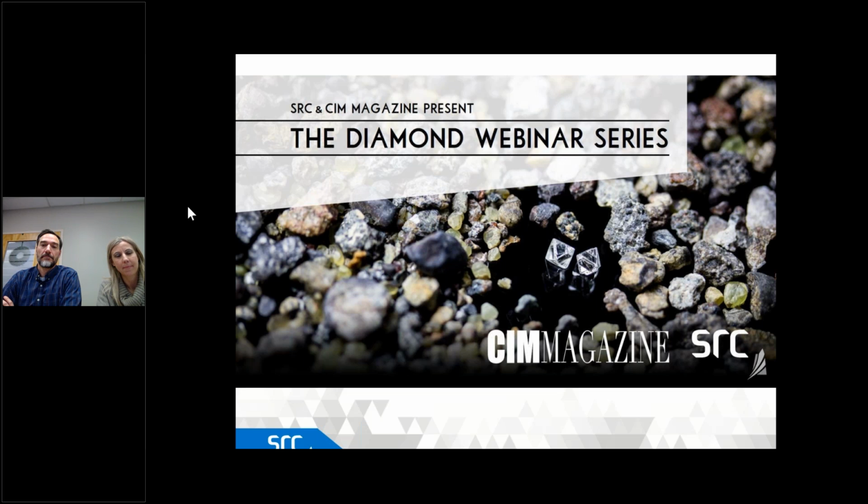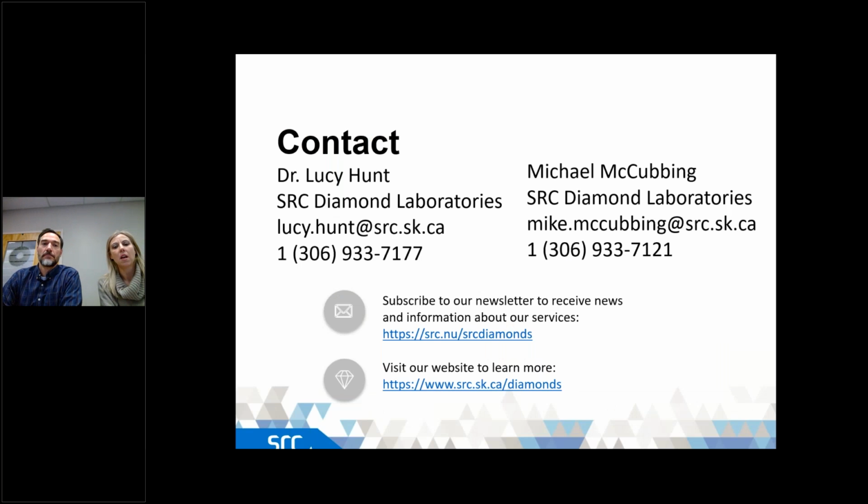Thank you. So can typing be done on micro diamonds? Yes, it can actually. We've gone down to about 106 microns, although we like to hover around 150 microns, which is the smallest we usually go. And this can have important implications in exploration if you're looking for kimberlites possibly with more type 2 diamonds, or trying to understand whether a certain kimberlite is related to another one, etc. So we have done a lot of typing on microdiamonds and how that relates to the macrodiamond populations as well.